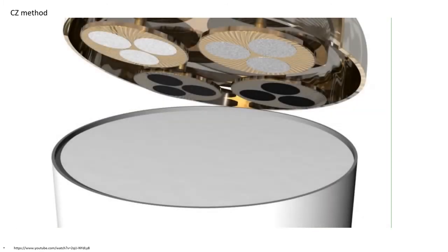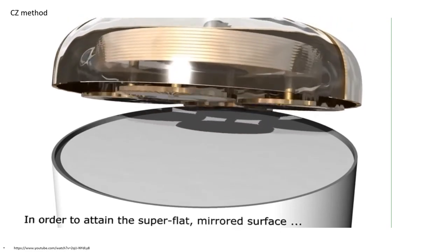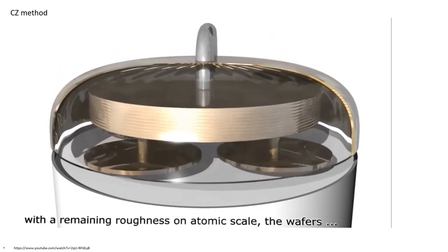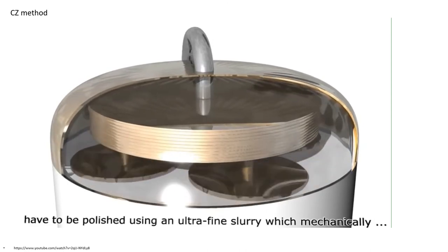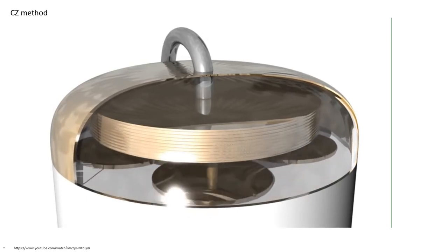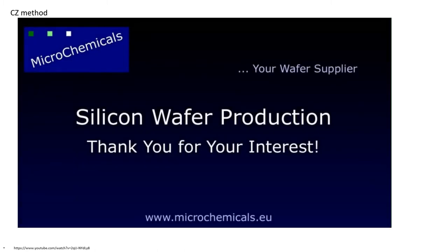Finally, polishing and cleaning is done. In this process, the silicon wafer is polished on the surface of a fine slurry. The slurry consists of alumina or ultra fine diamond particles. The rotating movements, along with the cushioning pads provided in the process, help in removing the very fine scratches on the surface.